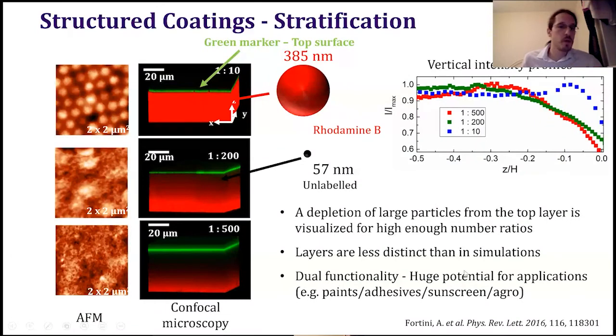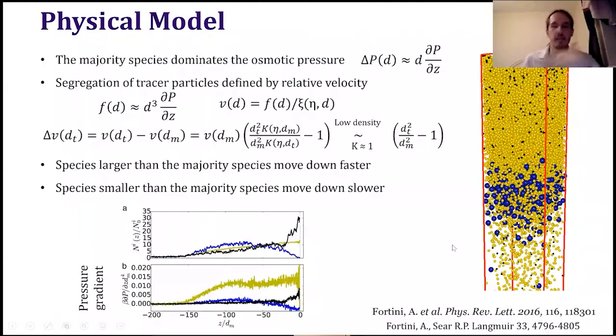And then the way in which we explain it, which I'm not going to go into detail on, is that basically we have an accumulation, a gradient in concentration of particles, from the top, where it is really high, to the bottom, where it is really low. So this is pushing all the particles down, but because the large particles have a larger area, the pressure on those is larger, and then they go faster to the bottom. So that's how we explain how they segregate.